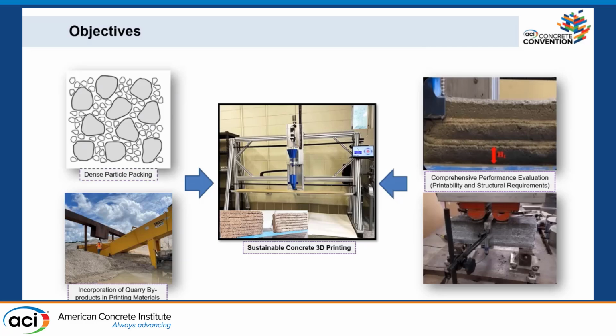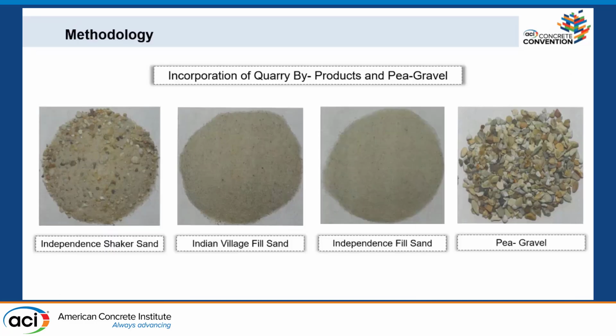For our project, our objective is to incorporate the quarry byproducts and pea gravel along with dense particle packing, and our goal is to 3D print these quarry byproducts and pea gravel dense packing mixes, with a comprehensive performance evaluation of the printed materials. We have got three byproducts from a local industry in Louisiana that are completely unusable to them. So we decided to test their properties and incorporate them with the coarse aggregate, that is pea gravel, for our project. The pea gravel is not larger than 9.5 millimeters in size.